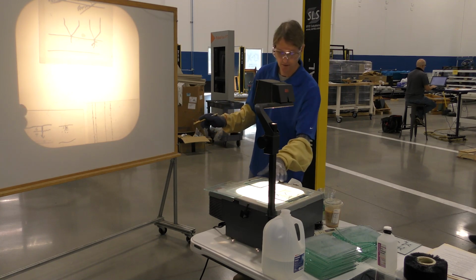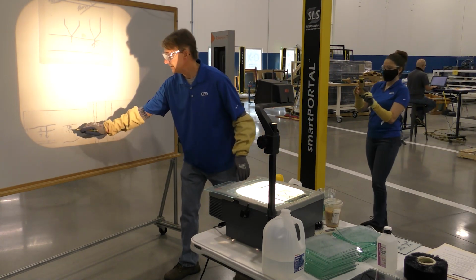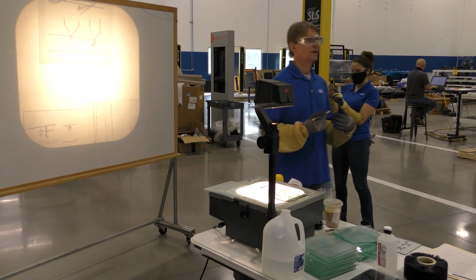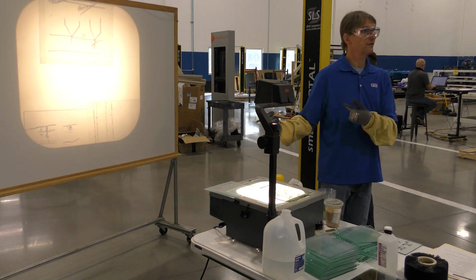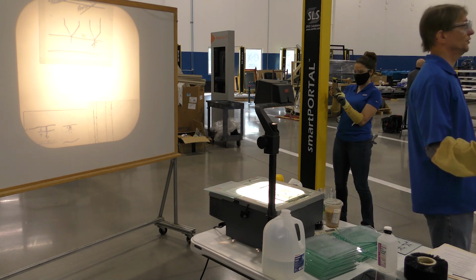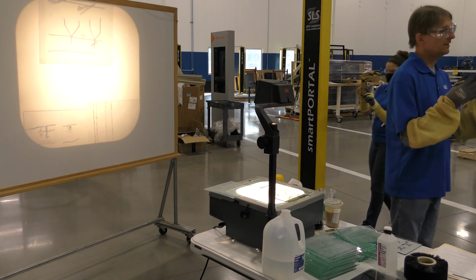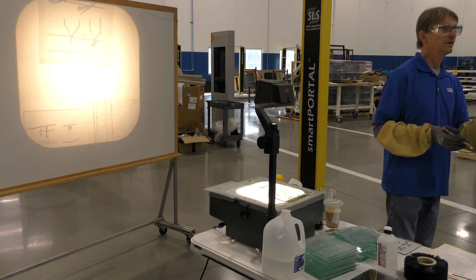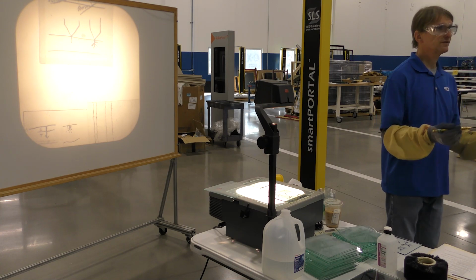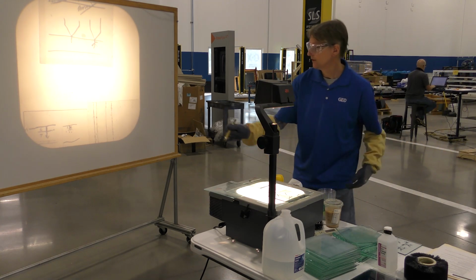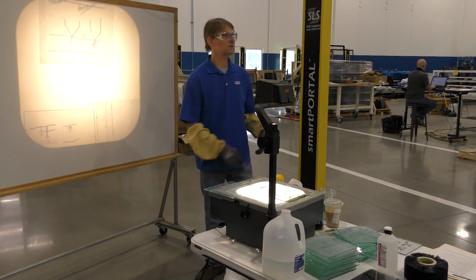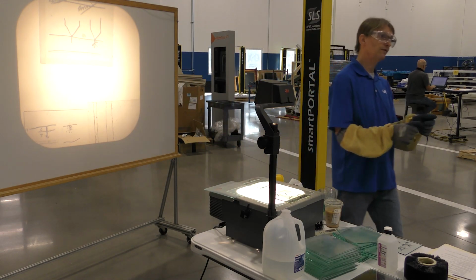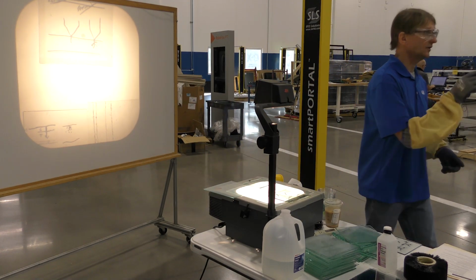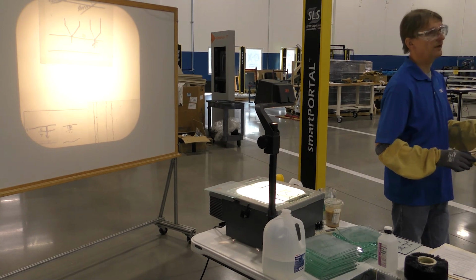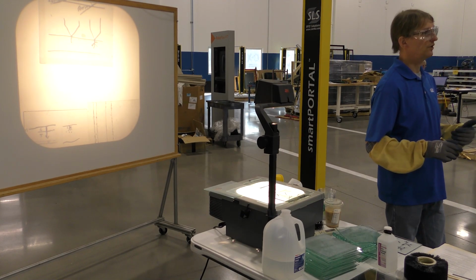If you score glass and you let it set for a while, you'll see it and you hear it relieving itself. All we want the cutting fluid to do is hold the energy into that fissure where it is until you break it out. Because over time what happens is it starts to disperse. All that energy starts to disperse and you lose the effectivity of making a nice break. And you're going to get crappy edge quality. You're going to get very poor edge quality if you wait too long.